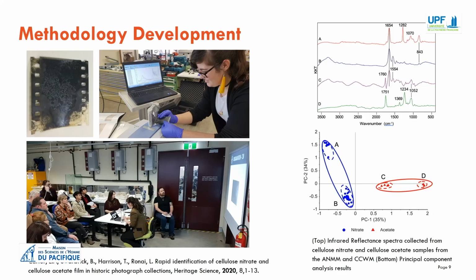At the time of this work, there was no single identification method readily available to heritage institutions that met the requirements to identify and distinguish between cellulose nitrate and cellulose acetate. In this study, samples from both the Sydney University Museums and Australian National Maritime Museum collections were analysed using infrared total reflection spectroscopy. Since the paper has been published, numerous institutions worldwide have used this methodology to characterise their often immense collections of cellulose-based films.